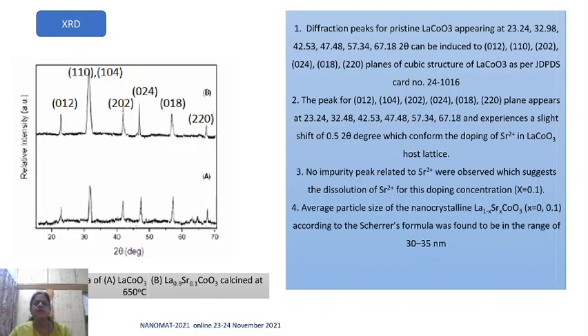Now, figure 2 gives the XRD pattern of Sr substituted LaCoO3. The peaks for 012, 104, 202, 024 and 018 planes are appearing at 23.24, 32.48, 42.53, 47.48 and 57.34. Here you can see that there is a slight shift of 0.5 2 theta degree, which confirmed the doping of the divalent Sr ion in the LaCoO3 host lattice.